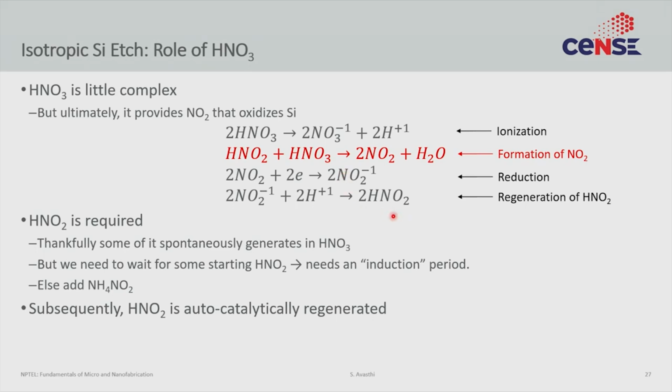And till that time, the reactant seems to just be standing still and doing nothing, but if you just wait it out, then you will see them becoming active again. If you are doing very shallow etches, if you are doing very careful etches where you cannot tolerate the induction period, or you cannot tolerate the variability that is introduced by this induction period, you can always choose to add some ammonium NH4NO2 into the solution.